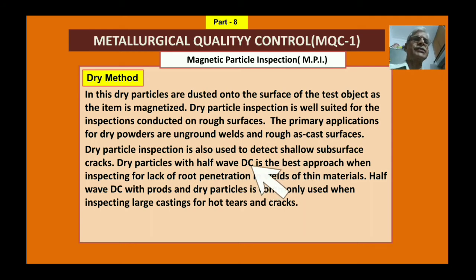Now dry particle inspection is also used to detect shallow subsurface cracks, as I explained earlier. Dry particles with half wave DC, which I have earlier explained, is the best approach when inspecting for cracks of root penetration in a weld. In welding, in root penetration, whether it is penetrated well or not, and if it is penetrated and there is any crack, then it can be seen with this half wave DC only. Otherwise you cannot see it.